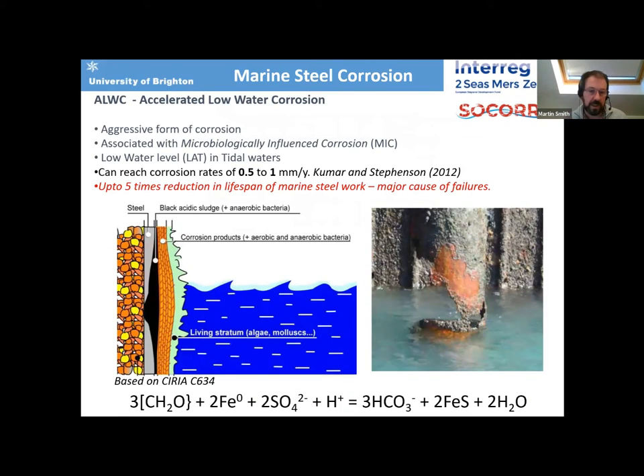So what particularly interested us at Brighton and brought us into this area initially was this phenomenon called accelerated low water corrosion. So we sit in that low water corrosion area, low water enhanced corrosion area, and we bring in the microbial factors on top of that. And that combination of factors can give up to 0.5 to 1 millimeter per year loss of thickness from marine steelwork. That's up to 5 times reduction in the lifespan of marine steelwork. So it's a major cause of coastal marine infrastructure failures.